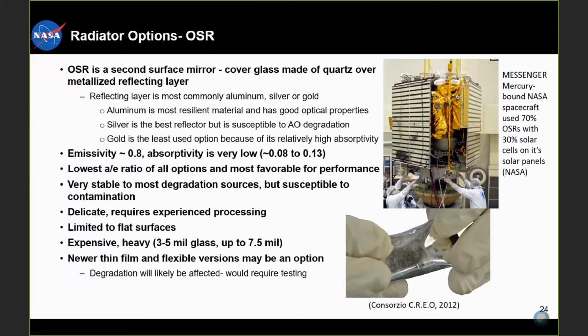So next we'll go through some different radiator options. The first one we'll discuss is the optical solar reflectors, or OSR. OSR is a second surface mirror. It's cover glass made of quartz over a metallized reflecting layer. This metallized reflecting layer is most commonly aluminum, silver, or gold. Just some characteristics of those reflecting layers. Aluminum is the most resilient material, and it does have good optical properties. Next is silver. It is the best reflector, but susceptible to atomic oxygen degradation. And then gold is the least used option, because of its relatively high absorptivity.